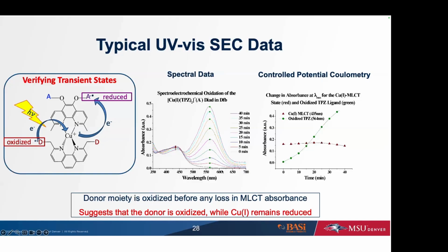And we were able to see that in our absorption data, and I realized right now that I just pulled the wrong graph, so apologies. This is not the coulometry graph, this is a different plot of the change in the absorption spectra. But this was the outcome, that we were able to correlate these changes in absorption to the changes in the concentration of the donors and the copper, and that's how we were able to relate it back to the stoichiometry. So while I have 2 absorption graphs on here, you also get a coulometry graph, which would tell you how many electrons have been passed through your system, and that helps you also to verify the stoichiometry.